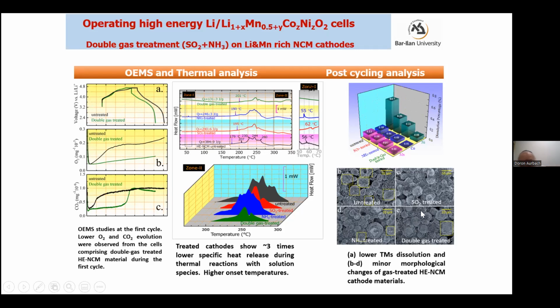So comparing untreated material and single gas treated materials, we see that the double gas treated, what we consider a winning process, leaves the morphology very stable, in very good correlation with all the other measurements. So it's nice to see here that we have coherent results from different channels. So the stabilization effect is clear and is understood.